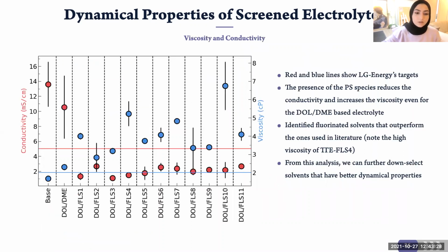We also computed the conductivity and viscosity, where for each electrolyte solution, the horizontal lines represent the desired limits, but we can see that most of them are not meeting these desired limits, even the conventional electrolyte, because of the presence of these polysulfide species that we included in the model. If we look at the base electrolyte that does not have any polysulfide, then it's meeting these limits. But once the polysulfide species are added, the dynamical properties are affected negatively.